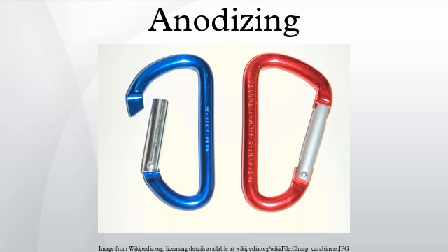The voltage required by various solutions may range from 1 to 300 VDC, although most fall in the range of 15 to 21 V. Higher voltages are typically required for thicker coatings formed in sulfuric and organic acid.